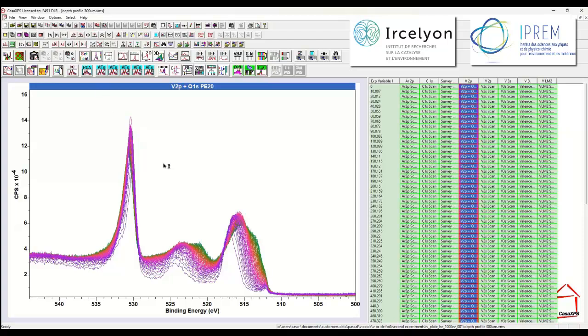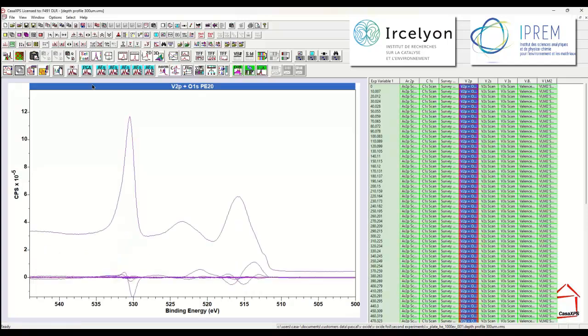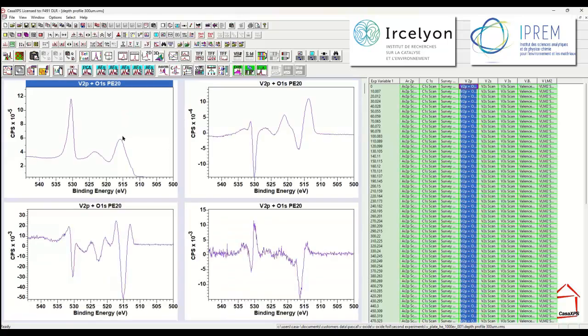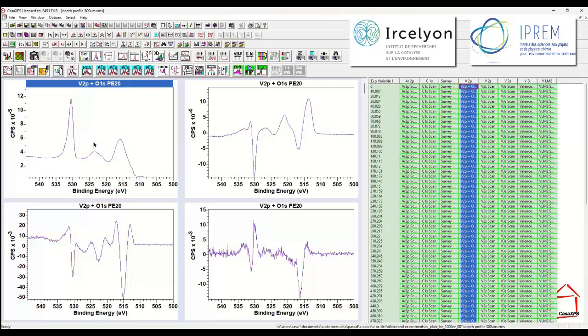So to find out how many shapes are within these data, we're going to apply Principal Component Analysis, PCA. And when I apply PCA to these data and then display the abstract factors, we can see that we have one that represents the majority of the signal in these data, and then subsequent abstract factors are corrections to this first one, and then corrections to the second one, and so on, that need to be applied if we're going to reproduce all of these spectra using a limited number of abstract factors. And this is the reproduction step where we're trying to eliminate noise.